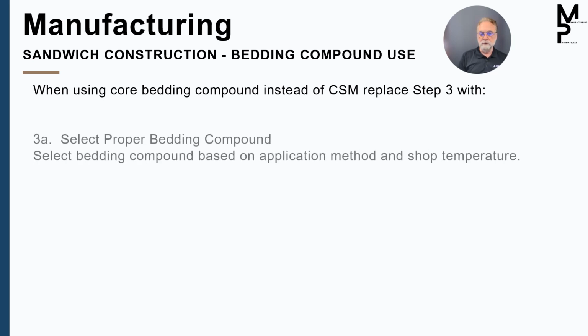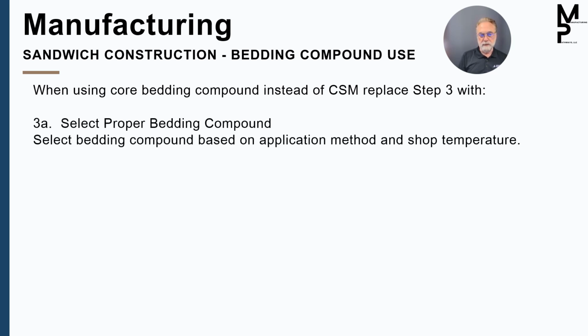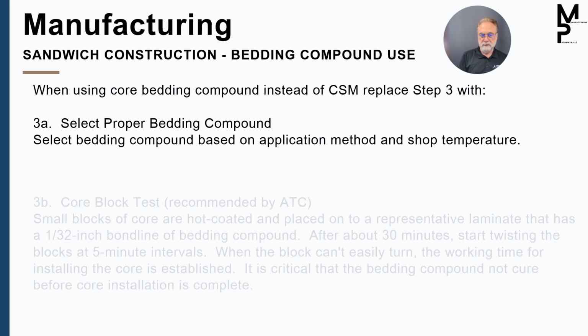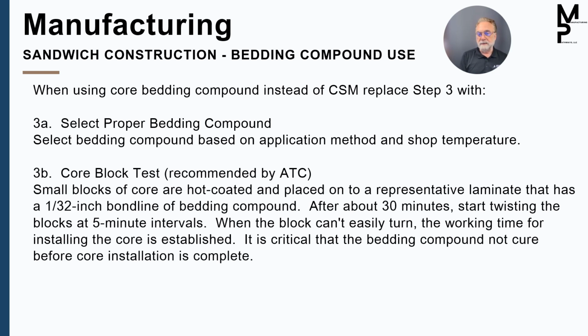Okay, now going to bedding compound in place of a chop mat to bed, you want to pick the right bedding compound for your temperature and your shop conditions. So we'll have different gel times, okay? And this block method is by one of the core manufacturers, and it works for all of them. So they want you to do a test off the part. So small blocks of core, we hot coat them with resin, and then we put putty onto a laminate surface, and the gel time is at least 40 minutes, so we wait 30 minutes, and after 30 minutes we start twisting the block, okay? And you'll feel it when the resin starts to gel, the block won't turn easily. That is the working time that you have to get the core in.